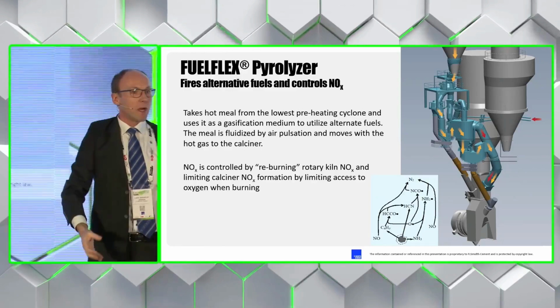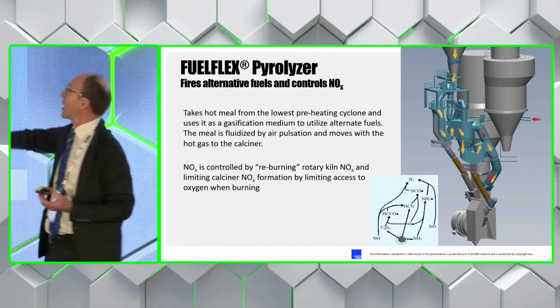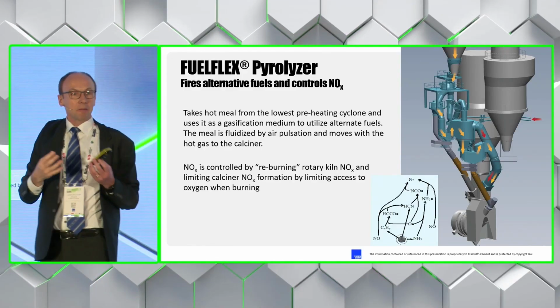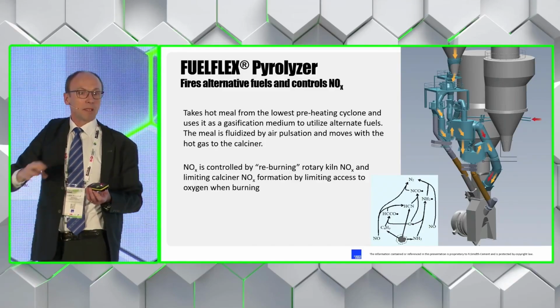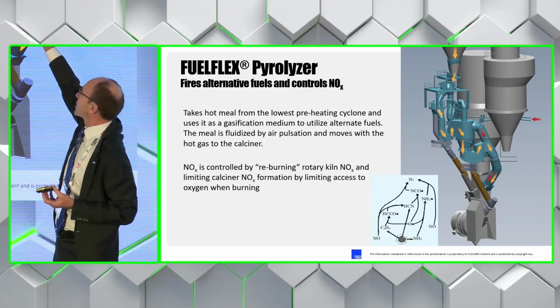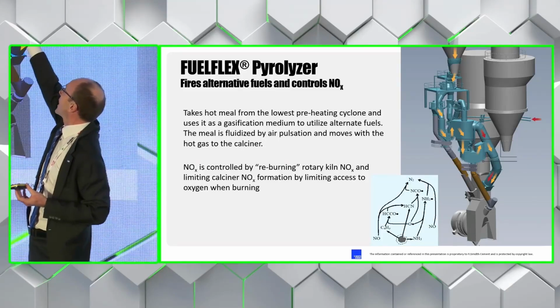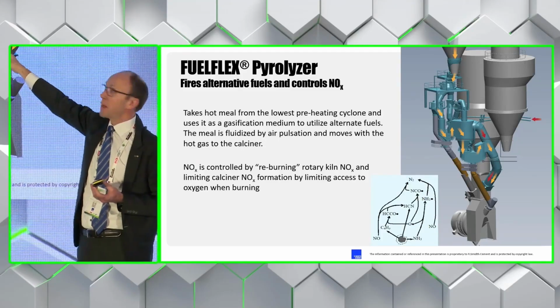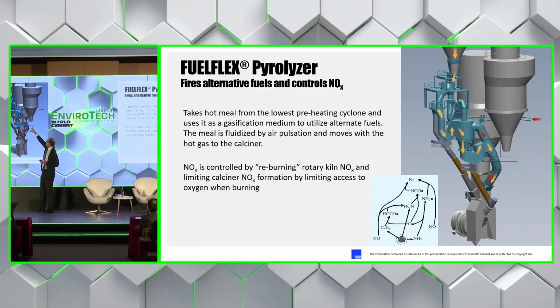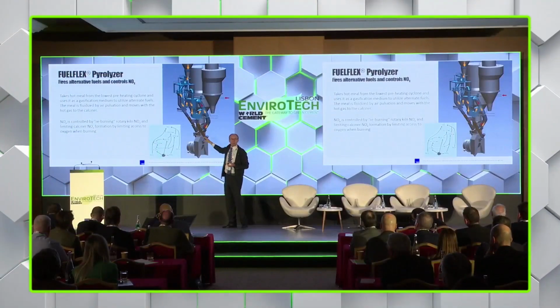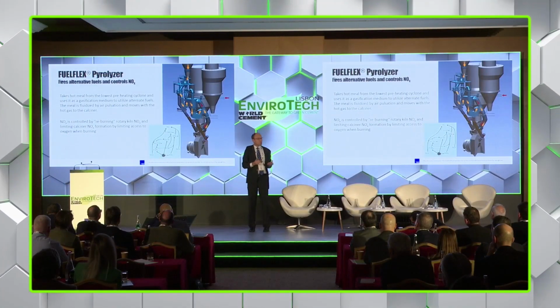As I showed before, it dries away the moisture, so the moisture goes upwards here. And after that, on heating up, it releases the volatile components, which also go upwards. The char goes down, following the yellow arrows here, together with the meal. The volatile components then come down with the red arrow there, meeting the meal, and then go into the kiln riser. And basically, this is the same position as we traditionally put in both the meal and the fuel.